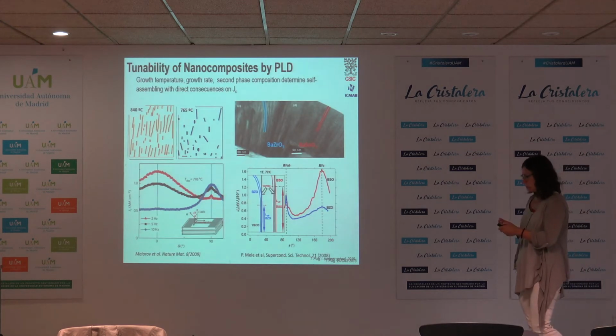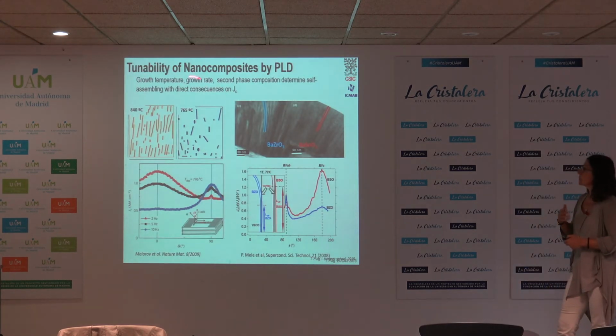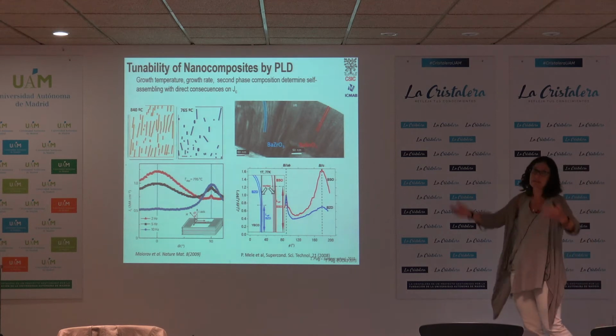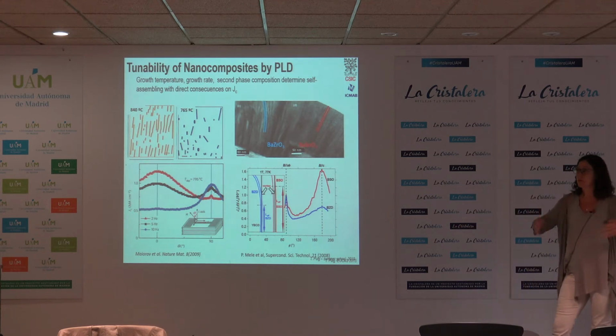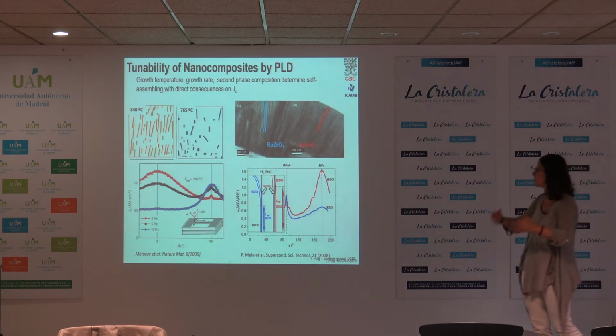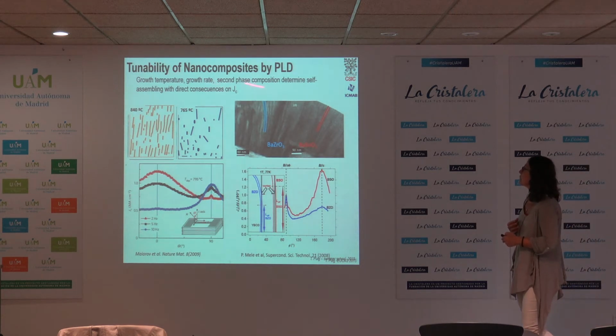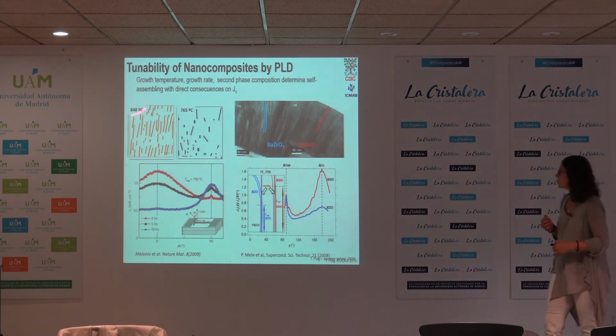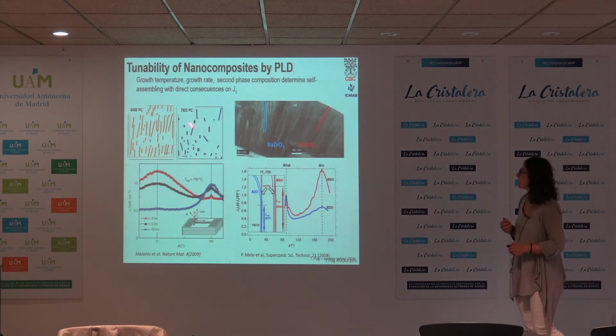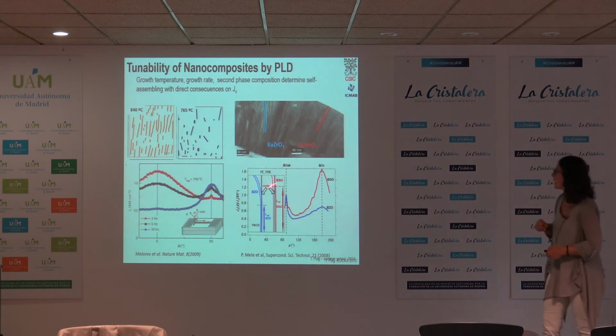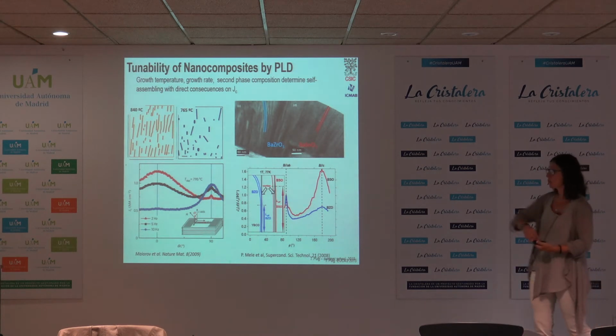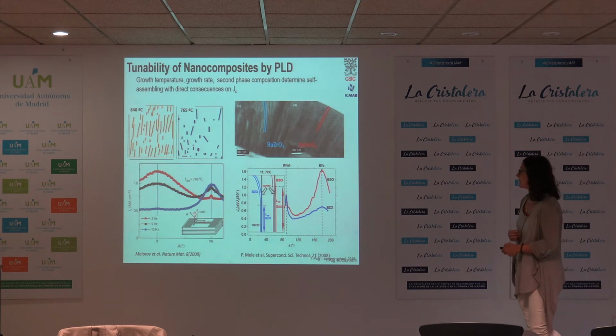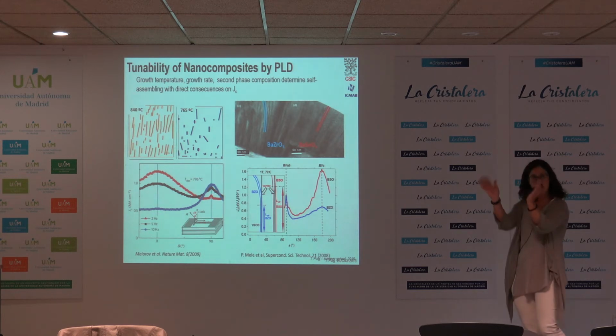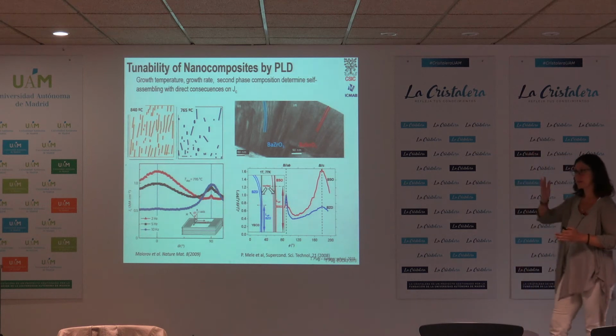In this case, you can play with the growth rate. In the case of pulse laser deposition, you can play with the laser frequency, for example, or the power of the laser, with temperature, with the composition of the second phase. And then you can end up with rods which are very short or rods which are very long that go through the full layer. You can end up with rods which get a bit out of the z-axis, or they are very strictly aligned.